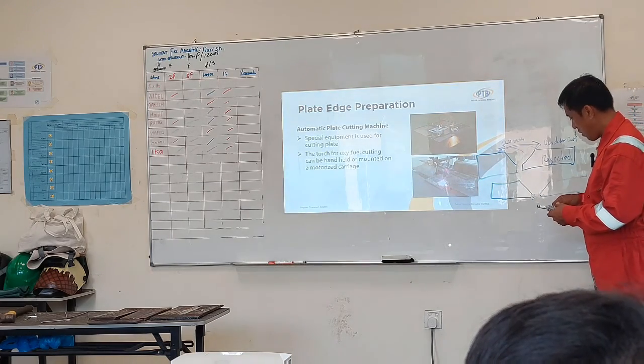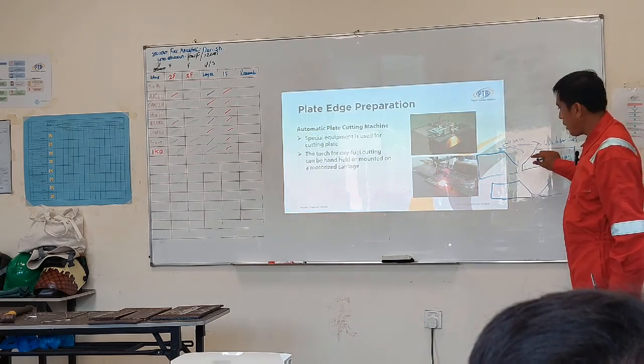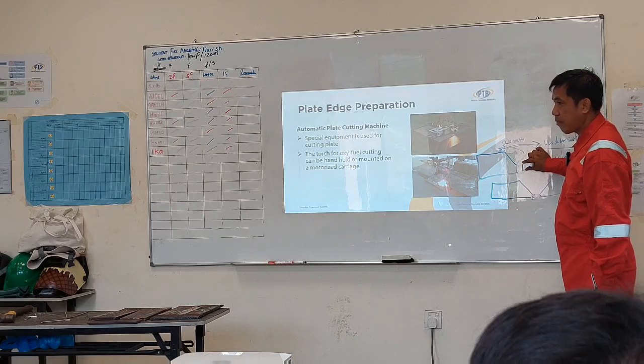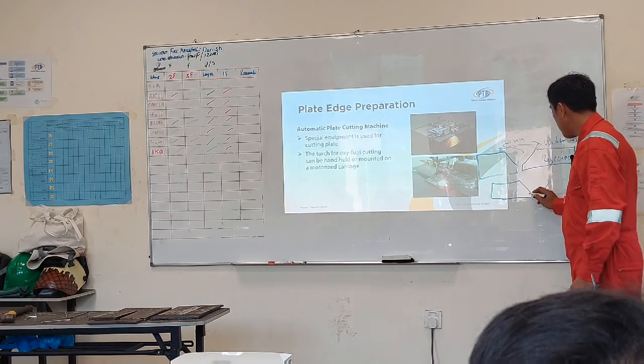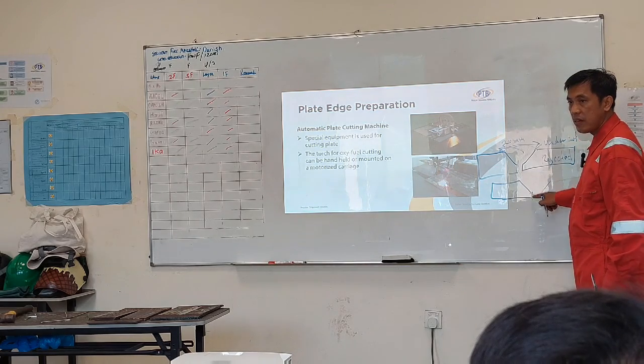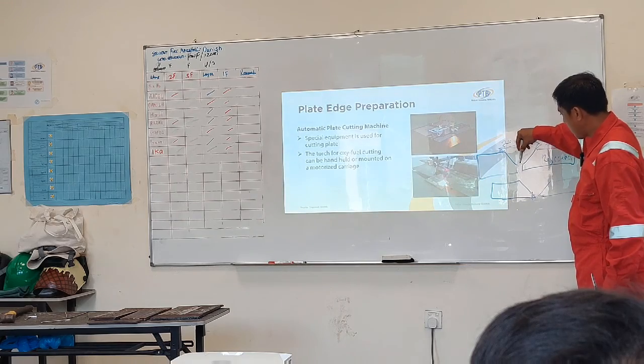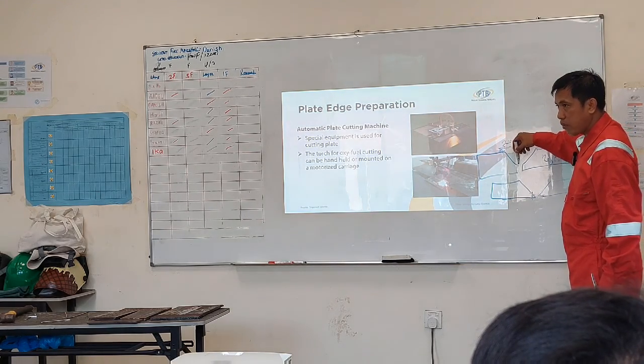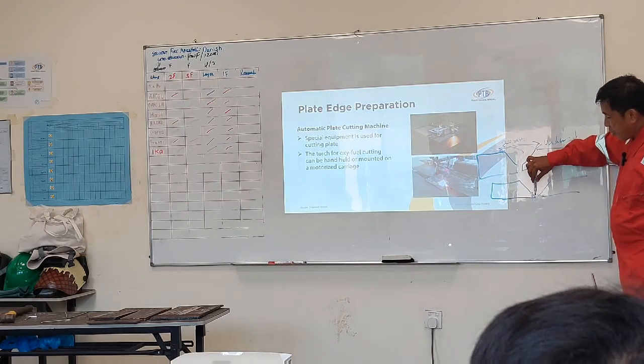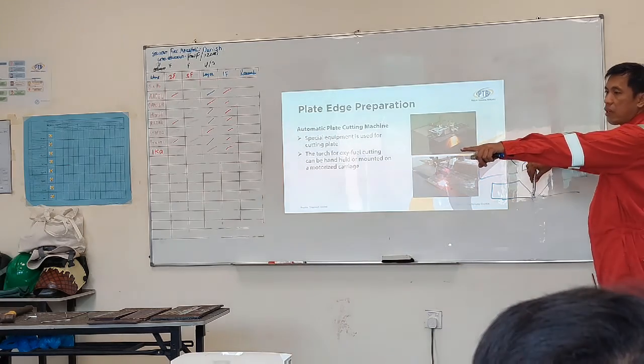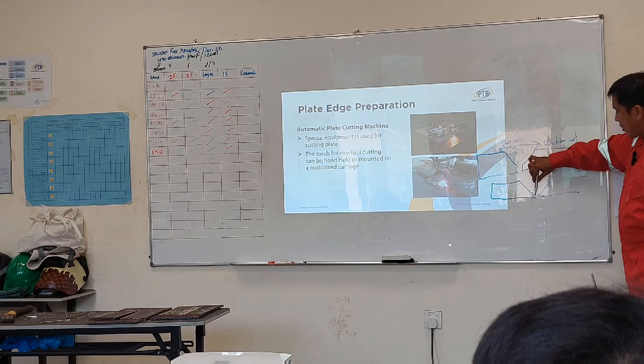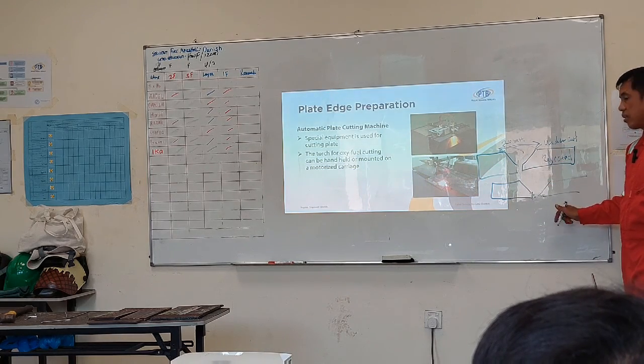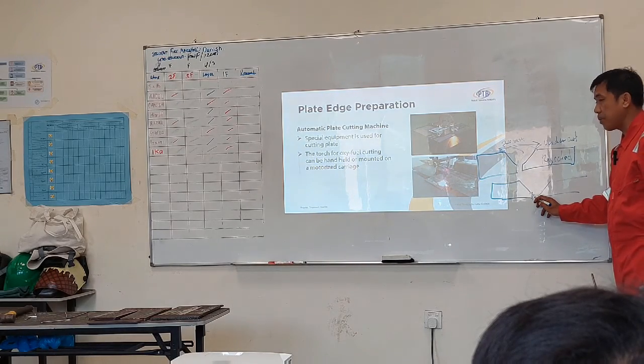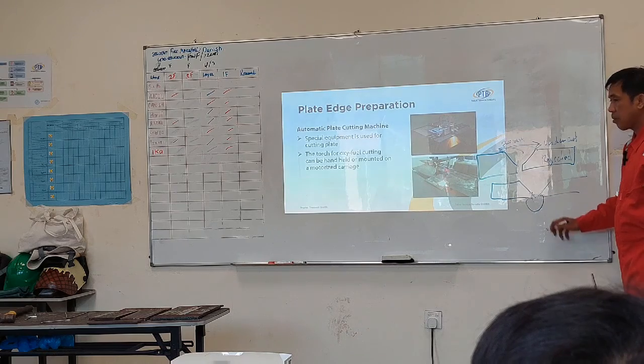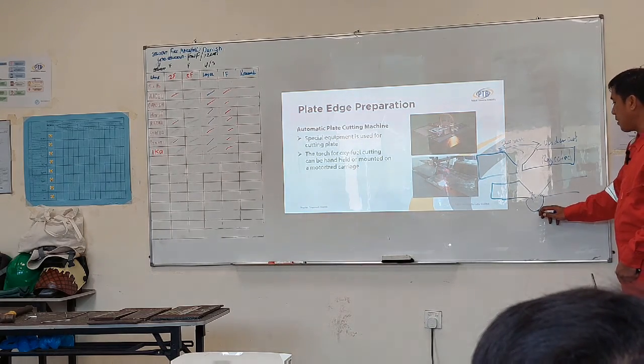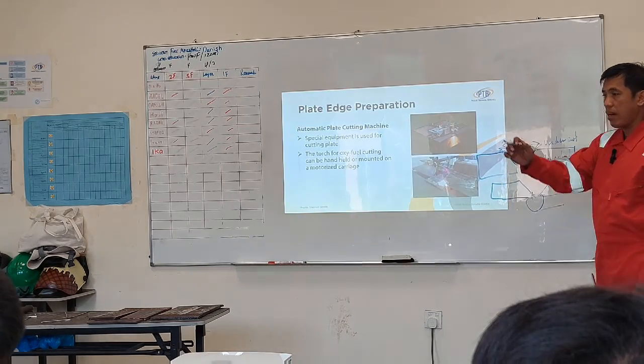Because if you can see, the root face is on this side, becomes thick, compared to without root face. You see the difference? If you start welding here, there's no issue if you weld with root face. If you start welding without root face using the same requirements, the same current, this one will burn through. And also, the root penetration at the back, if not burn through, is big, which is not accepted in accordance to the standard that we followed on the WPS.